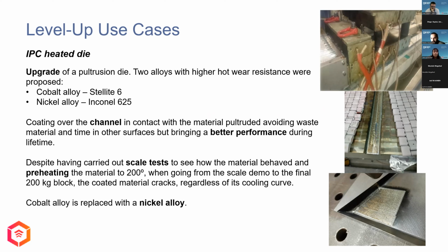Two materials were proposed, a cobalt alloy and a nickel. Firstly, some scaled tests were manufactured to test the manufacturability and the interaction between materials. Despite the fact that in the scaled tests the results of the cobalt alloy seemed acceptable, when we transferred it to the large part that weighs more than 100 kilograms, and even using a preheating machine, when depositing the first layers of cobalt alloy, a lot of cracks appeared and propagated through the coating.